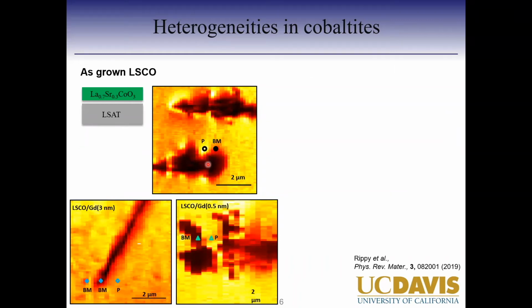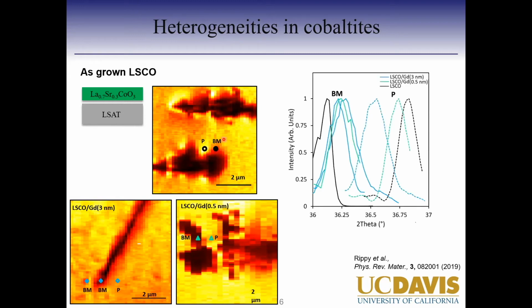And then the other thing, which I briefly mentioned, is that you can track your Bragg peak and map out the strain in the material. For example, we can sit at any of these locations and do a localized theta to theta scan. This is how a localized theta to theta scan looks. We have the as-grown LSCO, which is the perovskite here, and then the brownmillerite on this side. With gadolinium half, you start to see the perovskite peak shifting, and then 3 nanometer shifts even more.